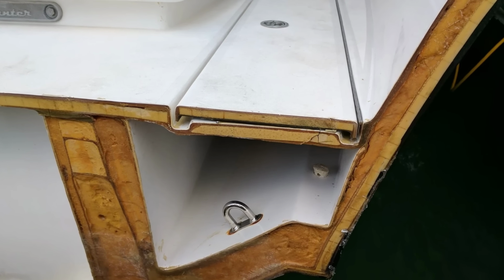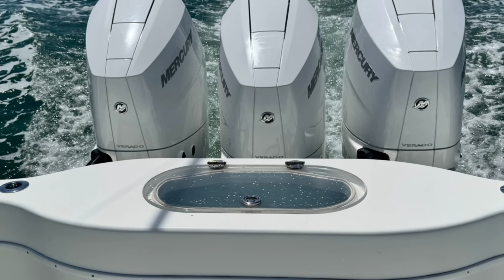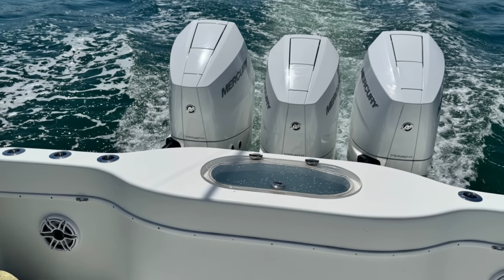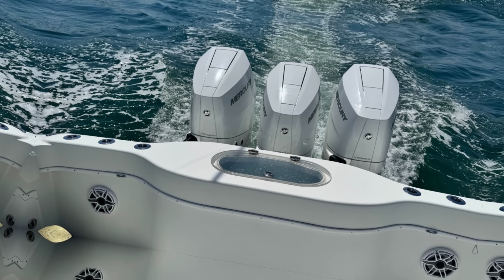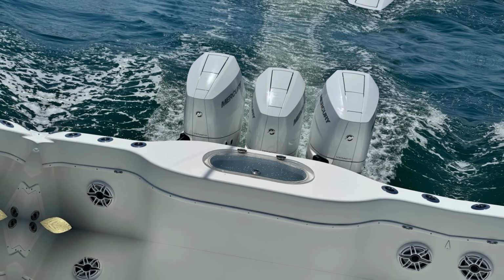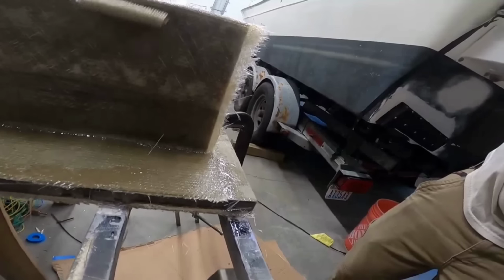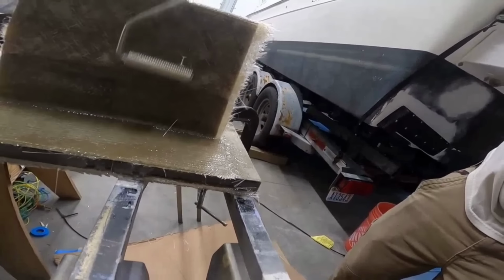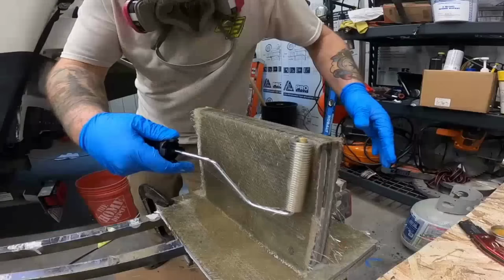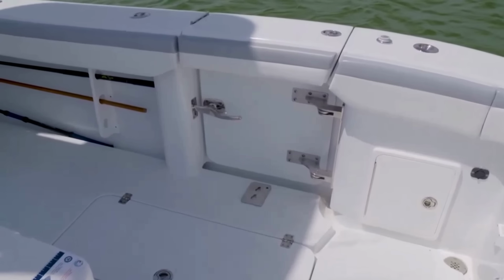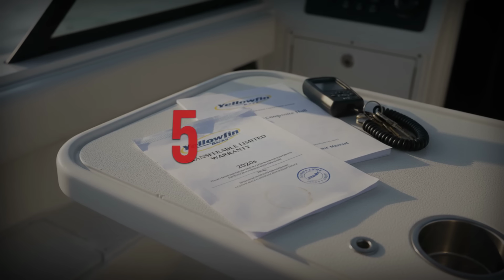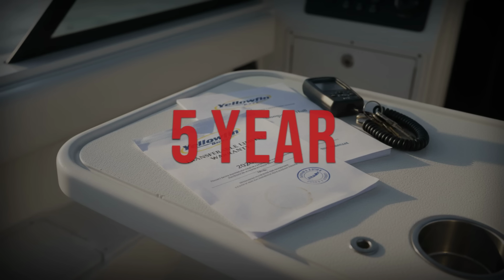Baltek core material is used in the running surfaces. Solid fiberglass surrounds all through hull fittings to prevent core saturation at penetration points. The stringer system is a box design using 2 layers of woven roving with injected foam, bonded to the hull and liner, and then fully glassed and tabbed throughout. The hull-to-deck joint is through bolted with 1/4-20 fasteners every 6 inches. The 34 Offshore carries a 5-year transferable limited warranty on the all-composite hull.